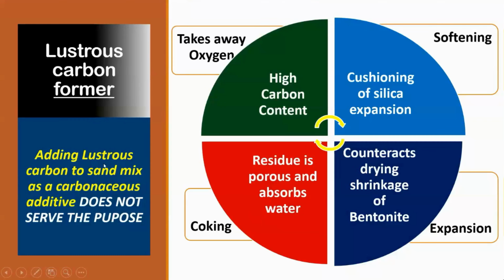So adding lustrous carbon to the sand mix as a carbonaceous additive does not serve the purpose. All that you require is a lustrous carbon former, which is in the sand. It can remain in the sand as long as it is not affected by heat. But when the metal is poured, that part of the lustrous carbon which is close to the metal in the mold is going to give all these benefits. Hence the surface finish improves.